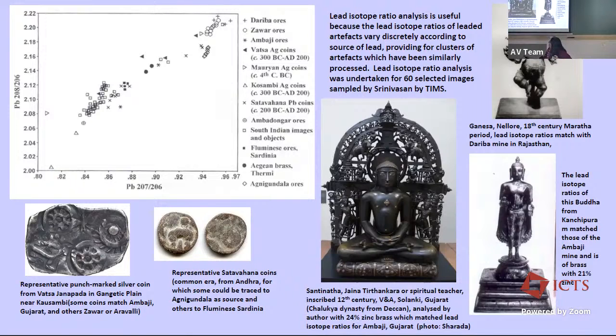Now, coming back to the lead isotope analysis technique, which, as I said, I'd managed to use for quite a large collection, 60 of them. I'd like to point to some interesting cases where you can actually identify the ore sources, because a lot depends on whether you do have the information for that particular ore source. And there's also the question of mixing of sources, because when the lead sources get mixed, then the isotopic fingerprints can go all over the place. But if the lead is from, say, one particular source, or maybe from two sources which have been mixed in a way that gives linear proportions, so there are all these nuances to how you can actually trace the sources.